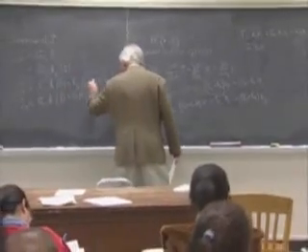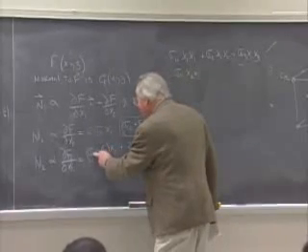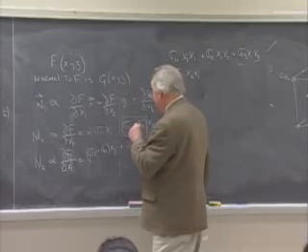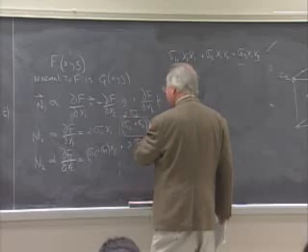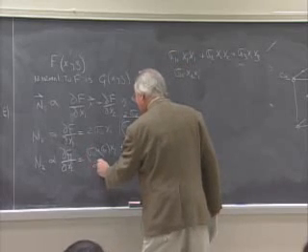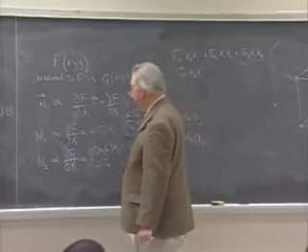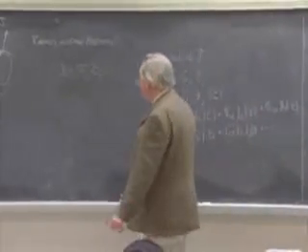So the conclusion we're forced to draw is that these two expressions would have components of a vector that are parallel to one another if sigma 1,2 was equal to sigma 2,1. Because if these were equal, I could write just twice sigma 1,2, and down here I could write twice sigma 2,1, and do that all the way through these two expressions. And then this factor of 2 would just be part of the proportionality constant.